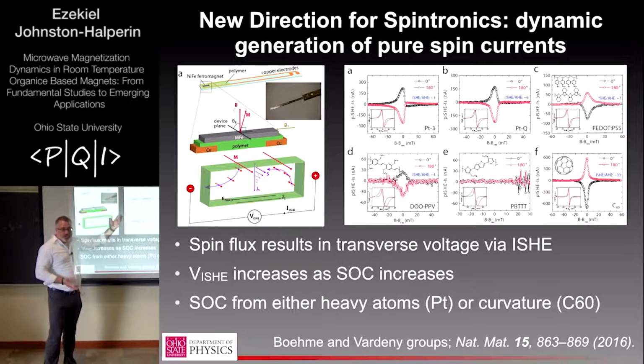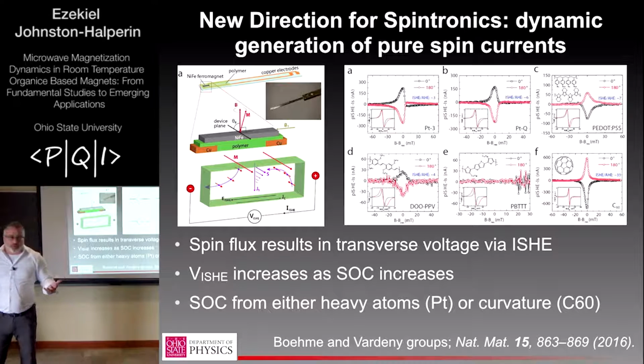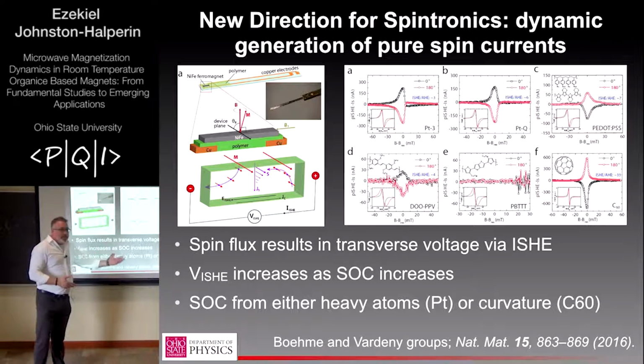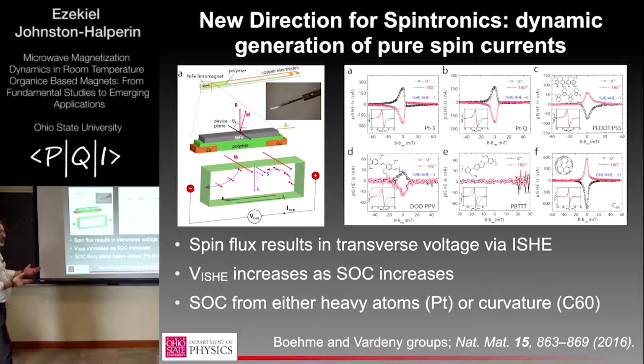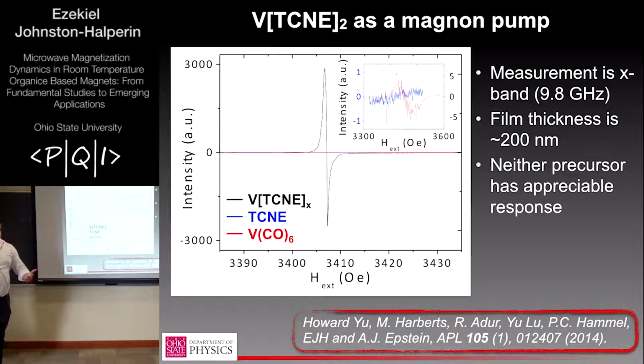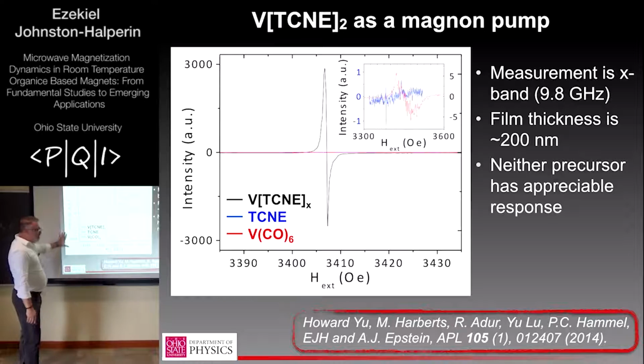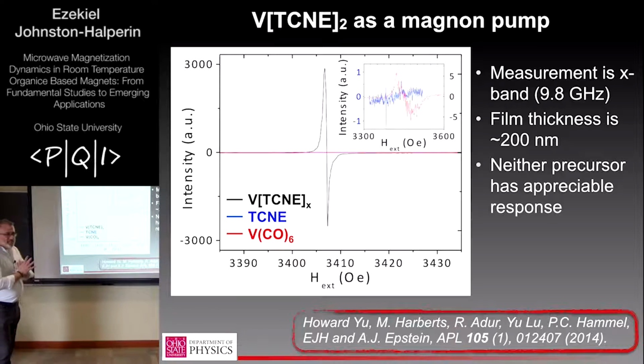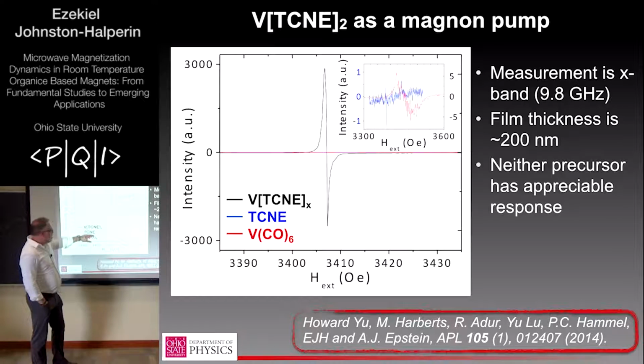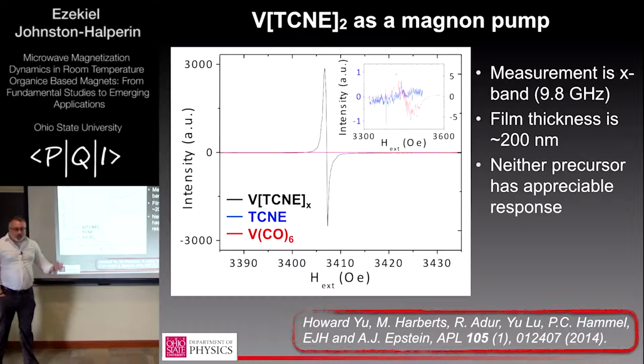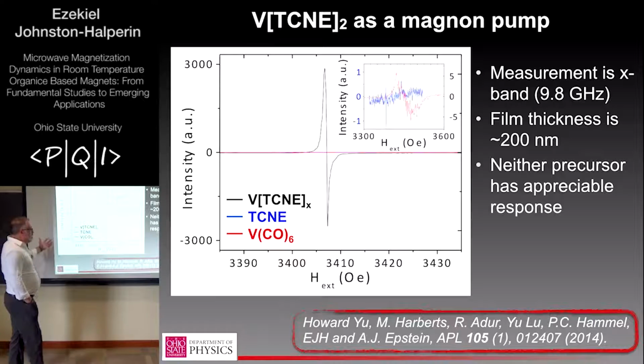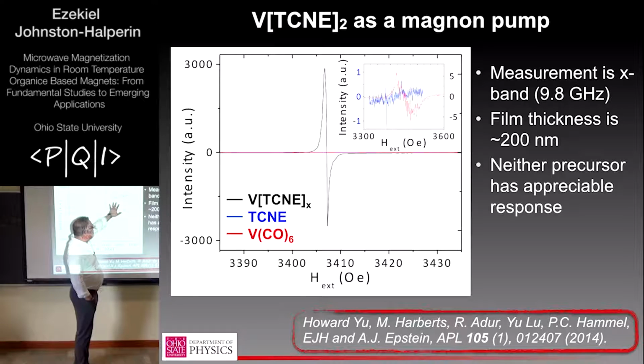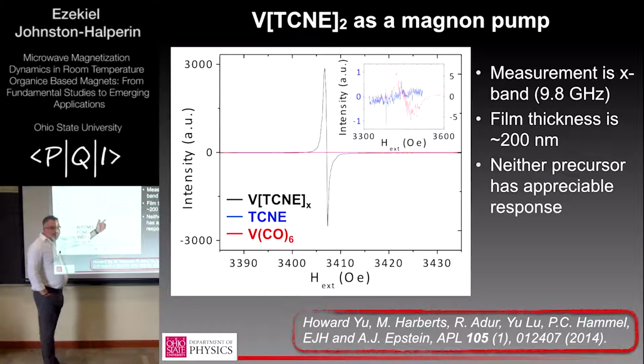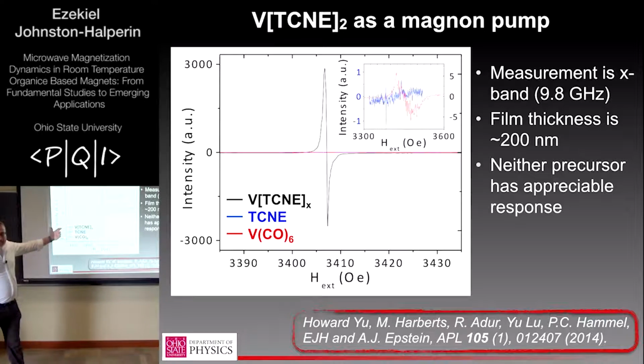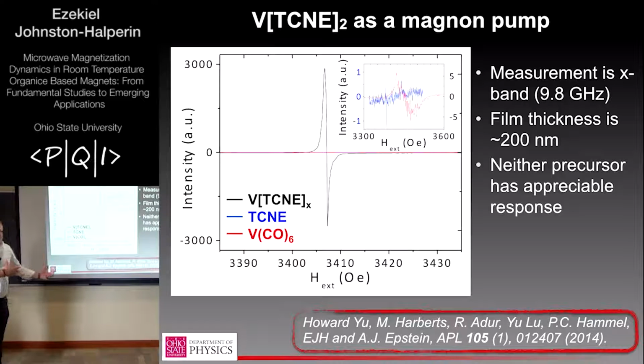But just like my earlier comments about organic electronics, in all of these systems, the organic is playing a passive role. It's the channel for spin. And so this was an impetus for us to consider the microwave resonance properties of VTCNE. So the question became, can VTCNE act as the pump in these systems? And so this is really, to butcher a quote, the FMR spectrum that launched 1,000 ships. Right? So this is just from a commercial EPR spectrometer, and you can see the line width for this particular scan is a little bit wider than 1 Gauss at 10 gigahertz, which is extremely sharp. And in fact, when we first saw it, the reason why there's this inset with control measurements is we looked at our two precursors to see if they were giving the same signal, because this looks like ESR. You just generally don't see FMR line widths that narrow. And so in the context of this new direction for spintronics writ large, we got very excited about the potential for this system.